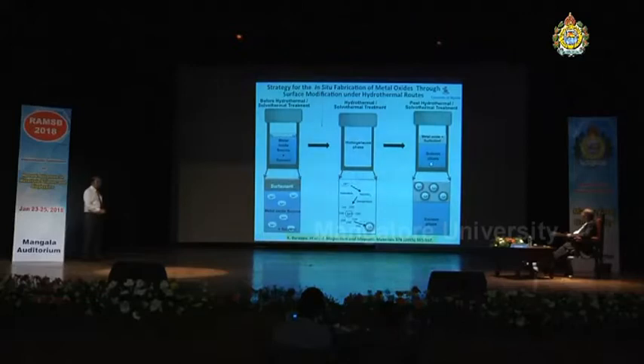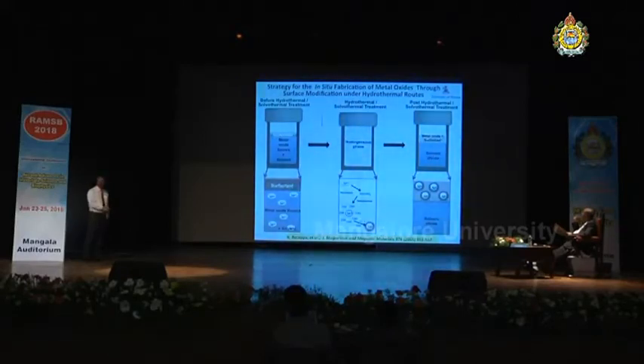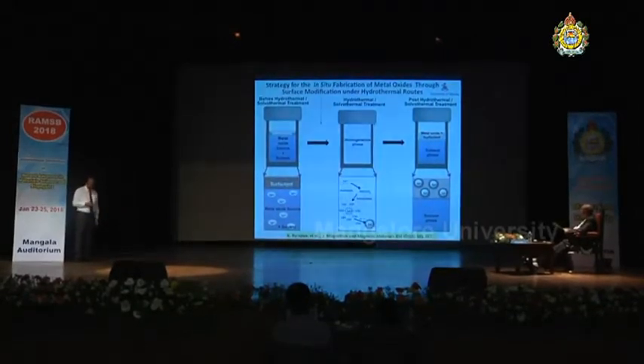And after the experiment, when you cool the reactor, you have the metal oxides and surfactants coming up, as you could see here, the surfactant at the top, but the metal oxides also move to the organic side, and you have the aqueous solvent which you can easily remove. And this is the popular strategy being adopted in recent years in the processing of metal oxides and other nanomaterials under hydrothermal conditions to give the desired or tailor-made properties, whether biological properties or physical properties, during the growth. That is why it's called in situ fabrication.